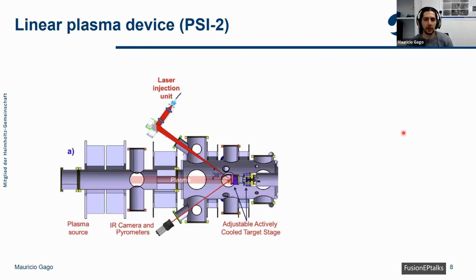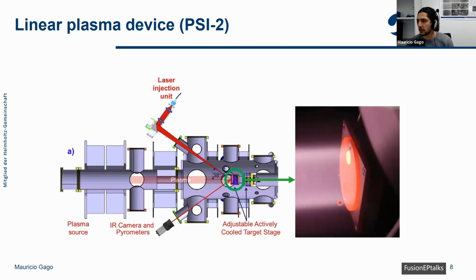So in this case, the linear plasma device, PSI2, was used. It can generate stationary plasma loads, so it has a plasma source. Here on this side, we have some magnets which can cause the plasma to hit the sample here. And additionally, we have the neodymium YAG laser, which can reproduce the transient heat loads which will be caused by ELMs. We can see here a sample being exposed in the device, and then the laser impinging on it at an angle.